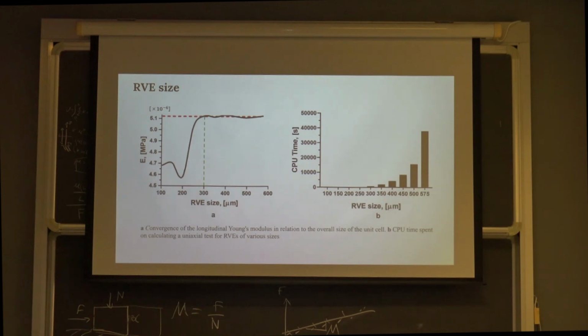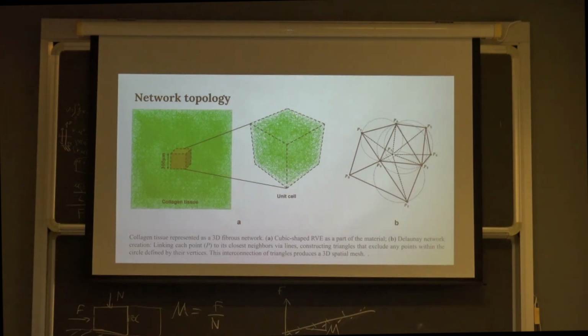So in all our experiments, we considered at least 10 different networks with the same parameters but different topology, and then we made the averaging. So how did we construct the network? As I said, we need regular boundaries. So initially we constructed a cube that has a regular network, and then we added random displacements to the points that are inside of the cube, and then we applied Delaunay triangulation to remesh the whole network, and finally we obtained the random network with regular nodes on the boundaries.